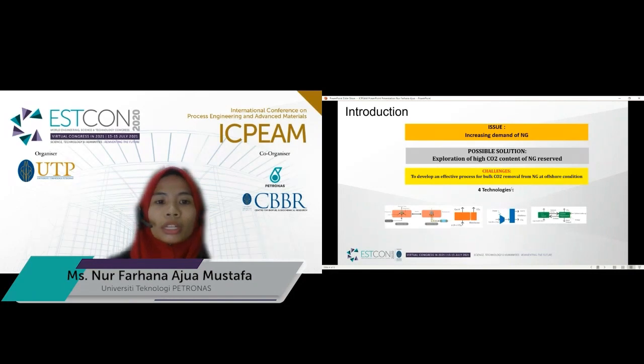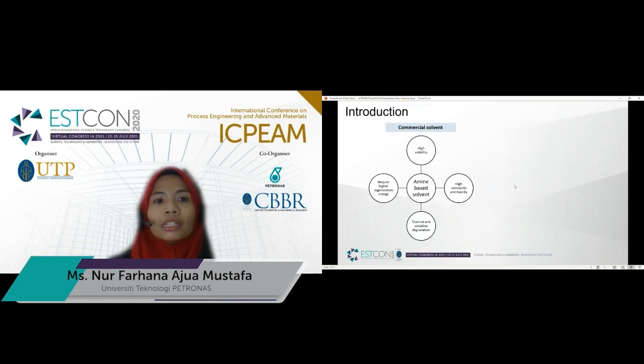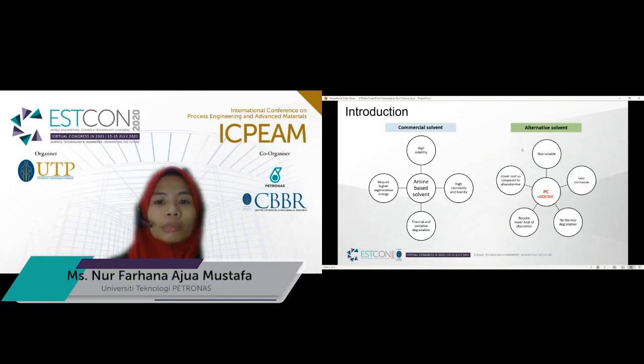There are four technologies that are well established, which are adsorption, membrane technology, cryogenic distillation, and absorption. In this project, we are focusing on absorption technology since absorption is the most matured technology as compared to the others. In absorption systems, the commercial solvent that is currently used is the amine-based solvent. However, amine-based solvent poses several drawbacks, which are high volatility, high corrosivity and toxicity, thermal and oxidative degradation, and it requires higher regeneration energy. In this project, we are using an alternative solvent, which is potassium carbonate with glycine. Potassium carbonate itself is non-volatile, less corrosive, has no thermal degradation, requires low heat of absorption, and has lower cost as compared to alkylamine.